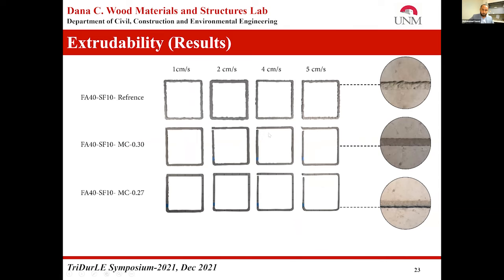A similar pattern was observed for another mix, that is FA40-SF10. And with the increment of the printing speed from 1 centimeter to 5 centimeters, we observe a similar pattern, the reduction of the printing parameters.